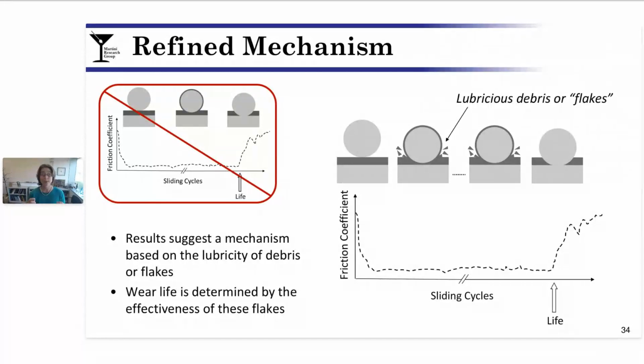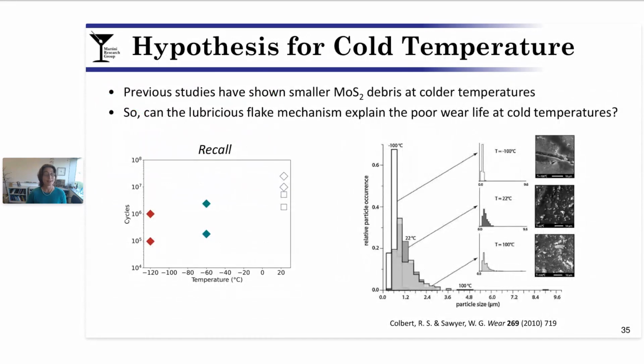They're lubricious debris or flakes that are available in the contact and ultimately are responsible for enabling the long wear life and determine the length of the wear life of each coating. So this is a pretty interesting idea, and it also enables us to try to move a little bit closer to understand some mechanisms. In fact, it could point us to a way to understand the cold temperature results. Recall that we saw that wear life was shorter in cold temperatures.